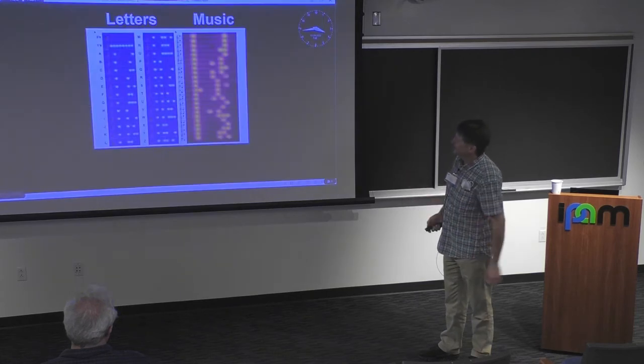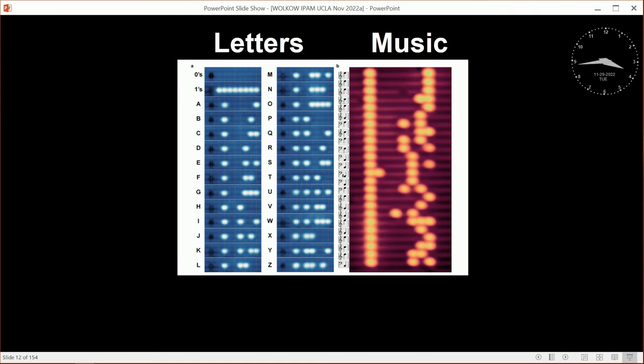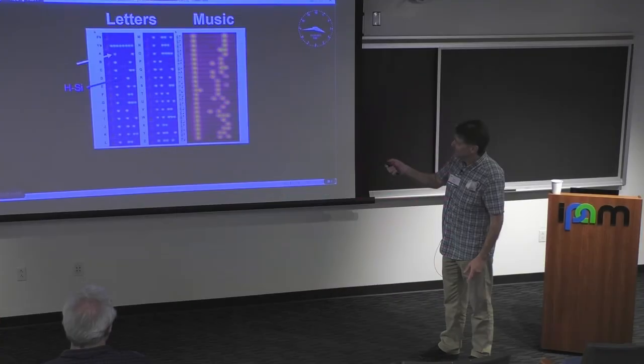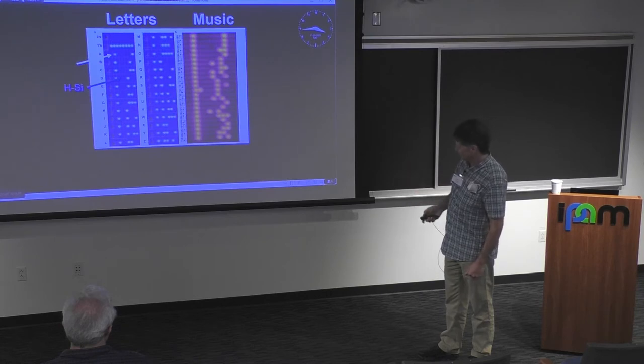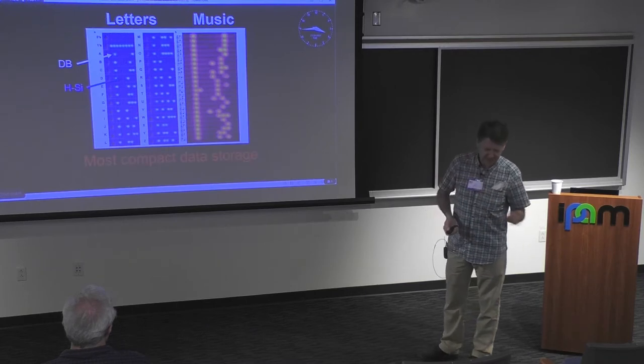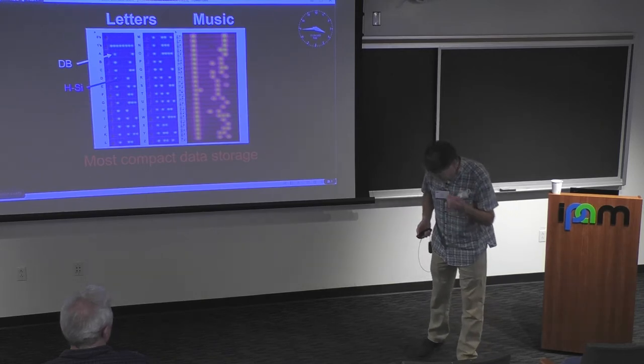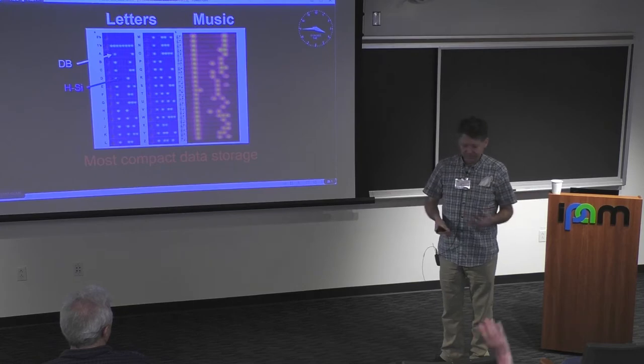Here's some examples of printing all the letters of the alphabet in binary ASCII code, just like in your computer. We took this little patch, put this defect on the end just as a marker, and we erased. So the blue areas are hydrogen silicon terminated, the white things are the dangling bonds. This is the same area written 28 times, where we erase it, write something, erase it, write something, whatever you want, as many times as you want. And someone couldn't help but write up the music for the Super Mario video song in atoms. So this is the densest information ever written. Now there are spectacular demonstrations from other groups who've put a molecule on a copper surface. They have similar density, actually. But their system just melts apart even if you get to 70K.